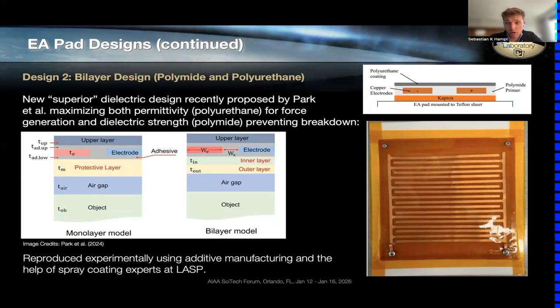The second design, which has been recently proposed, is aiming to address these material limitations. There's no single material that excels in dielectric strength and dielectric permittivity. So this concept proposes to use a bilayer design. First, use a baseline bottom layer that has strong dielectric strength, which is typically a polyimide, and then use a secondary layer that has very high dielectric permittivity, a polyurethane. So we had coating experts at the Laboratory for Atmospheric and Space Physics help us to build and manufacture such electrodes. The process that we used is we had a Kapton backing, micro-etched copper electrodes, chemically etched, professionally done by a company, and then had the experts at LASP spray coat this electroadhesion pad, first with a primer and then a polyurethane coating. The result is shown on the right.